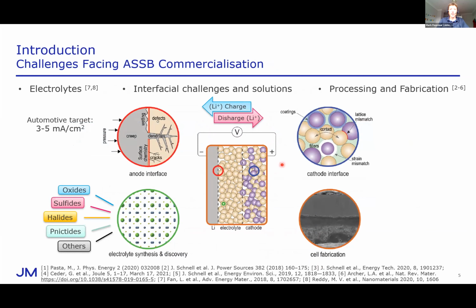So in an all solid state cell, we have a composite cathode, which comprises your electrochemically active material, lithium cobalt oxide, for example, in close contact with your electrolyte ceramic material, and there'll be carbonaceous materials in here to impart electronic conductivity, whilst the electrolyte material takes care of ionic conductivity. During charging, the lithium ions pass out of your active material through the electrolyte and are plated out at the lithium metal anode. Then during discharge, the lithium ions are stripped back from the metal anode, pass back through the electrolyte, and are recombined with your active material in the cathode. This repeated electrochemical cycling is accompanied by a whole raft of physical and chemical processes that occur mainly at the interfaces in these cells.